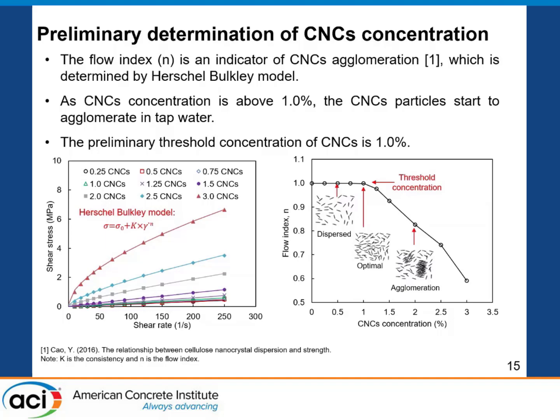As you can see in this figure, with a high flow index, we usually observe good dispersion of the CNCs in the suspension. But when the flow index n starts to decrease, the CNC starts to agglomerate. So from these results, we have determined a preliminary threshold concentration of the CNC as 1%. Further experiments have to be done to finalize this threshold concentration, as the CNC in water is very different than in cementitious systems.